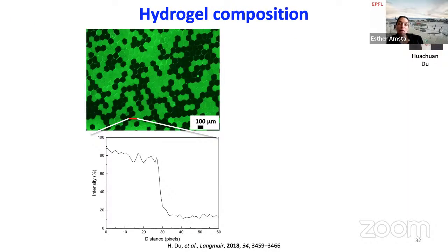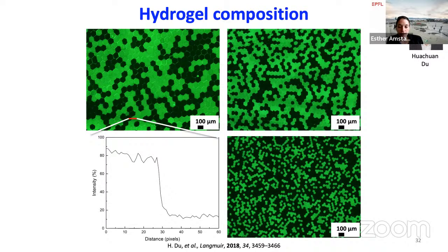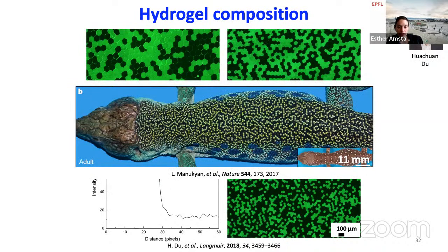And we could then abruptly change the composition of these hydrogels by mixing different batches of drops that have the same size but different compositions. Now, if you look at these patterns and you look at the skin of lizards, you see some striking resemblance, with an important difference, I think. Here, in our system, we cannot determine whether this particle, for instance, is black or green. This is just random. I don't think nature assembles these tiles in a random way. And to gain a better control over local